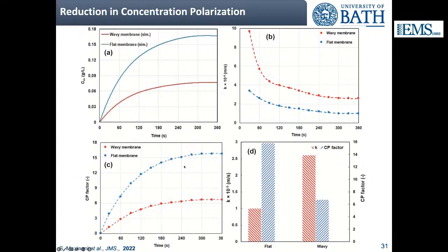But what I would like to highlight is the 2 plots at the bottom. Let's go with the bottom left. This is the concentration polarization factor. So the higher it is, the worse the concentration polarization effect. And you can see that for the wavy membrane, you have significantly less concentration polarization buildup than for the flat membrane. Again, the dots are experimental data, and the curves are the CFD modeling. And at the bottom right, you have a summary of mass transfer coefficient and concentration polarization factor. In the case of the wavy membrane, you have a high mass transfer coefficient and a low CP factor, and of course, the opposite is true for the flat membrane.